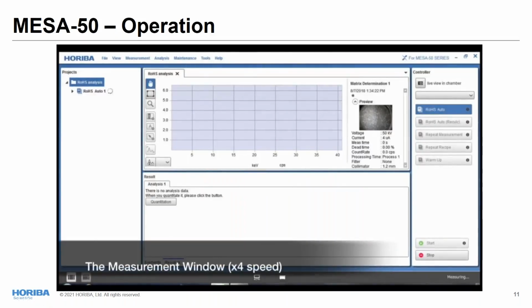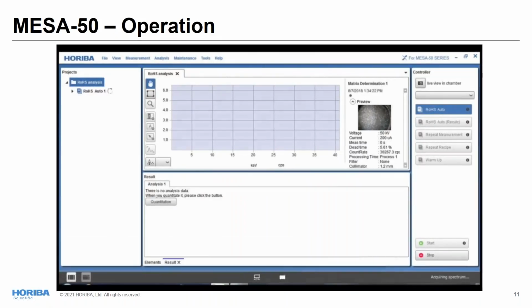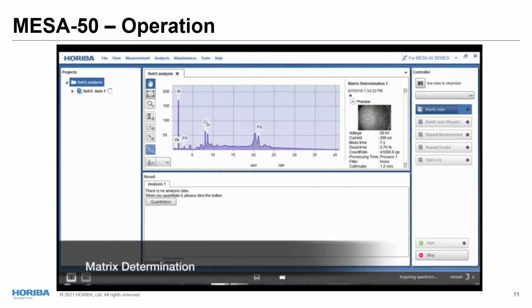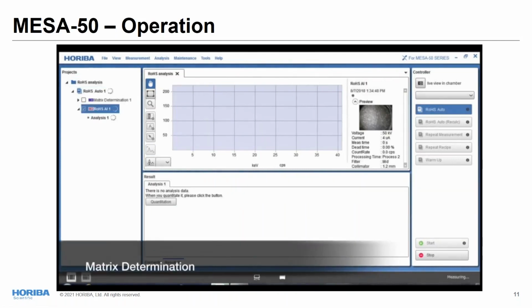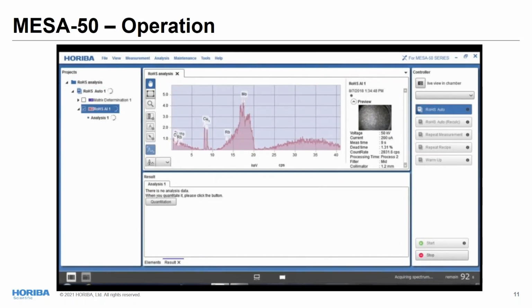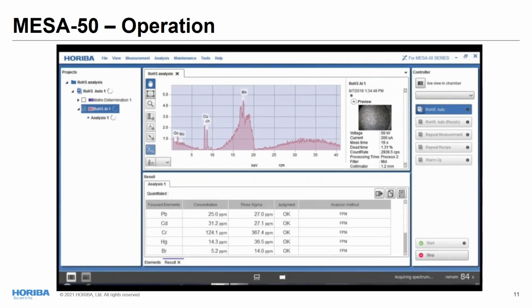The analysis can be done in one step or sometimes two steps to measure major elements at high concentration and eventually lower concentration elements that may require different settings. At the end of the analysis, the system will give you a table with the concentration of each element detected, using the fundamental parameter method or the calibration that you performed before.